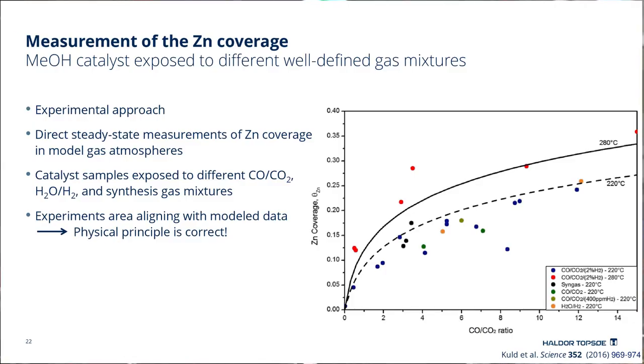But this is only a model. Of course, it needs to be verified, so we took an experimental approach. By means of these chemisorption measurements I showed you before, it's actually possible to measure the zinc coverage directly of the system after exposing it to different gas atmospheres. So here you see all the results.